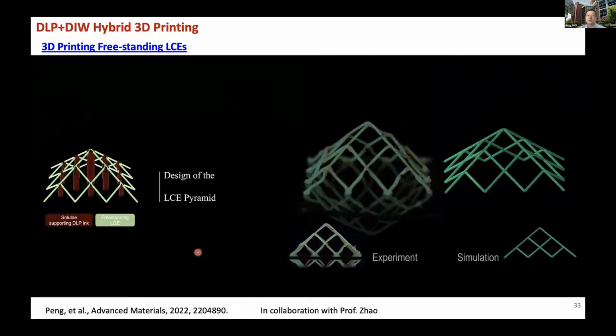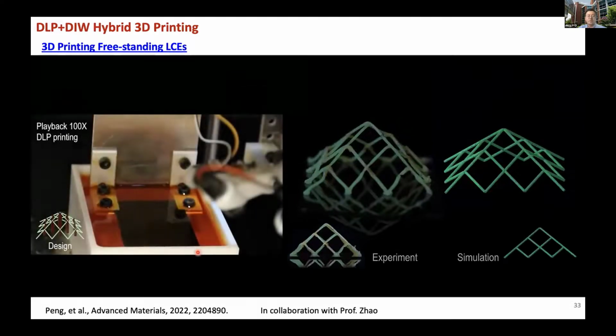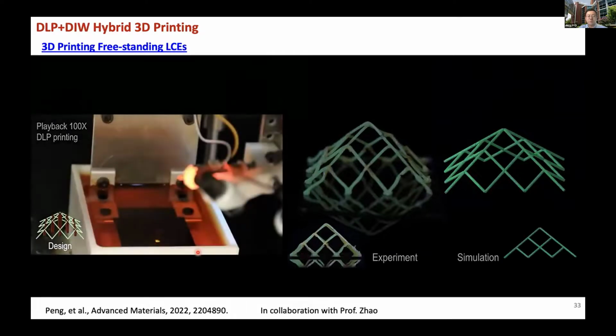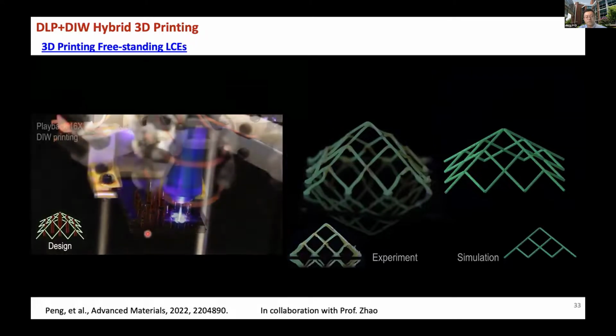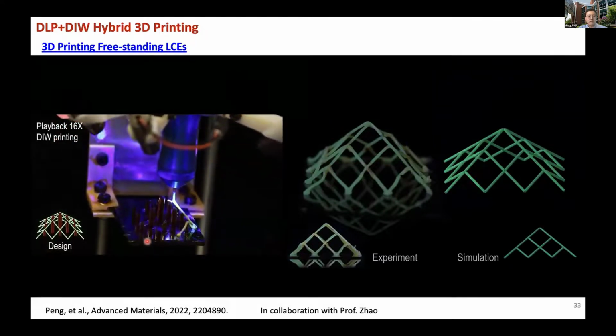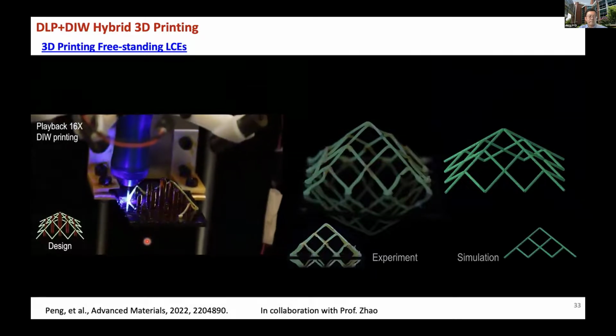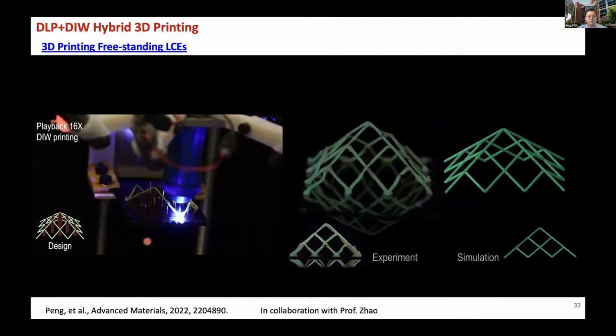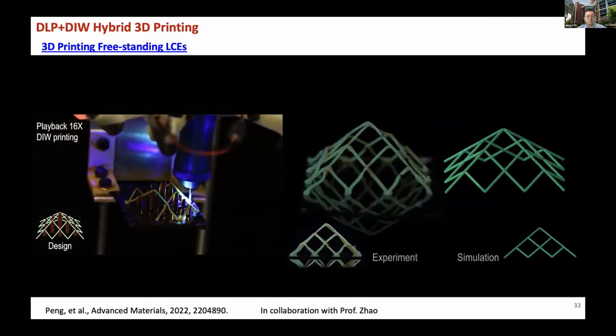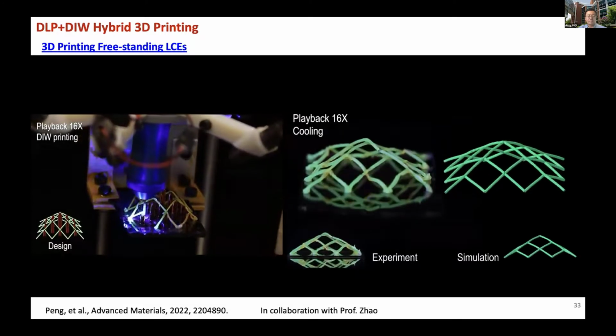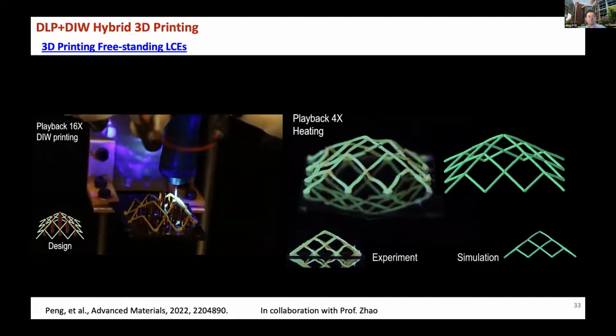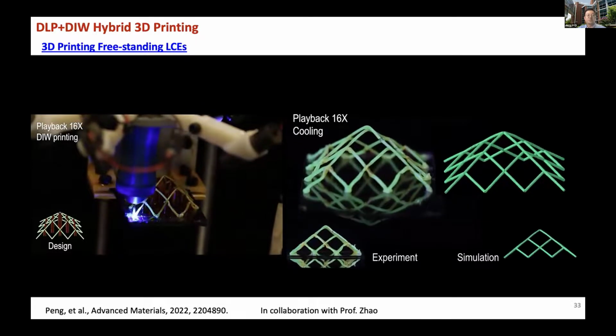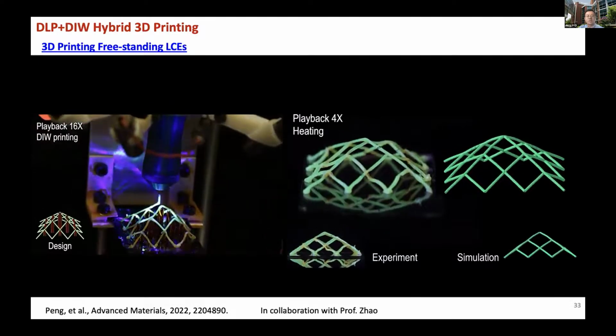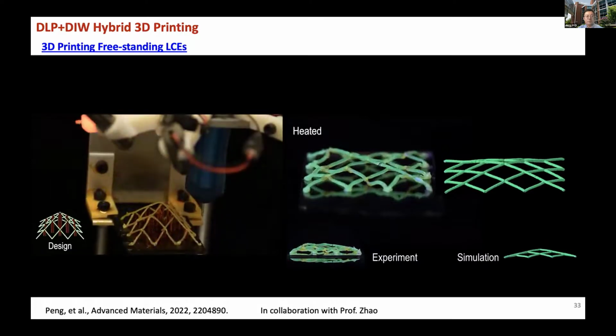We can also print a 3D lattice. This is a 3-dimensional pyramid on the surface. In this case, we're using a dissolvable DLP ink. So we first printed the support structure using the DLP, and this got rods. And then he wrote this kind of LCE on top. After this printing, he took it out and put this structure in water for 4 hours, and the DLP printed part would just be dissolved away. And after that, you got the freestanding pyramid structures.